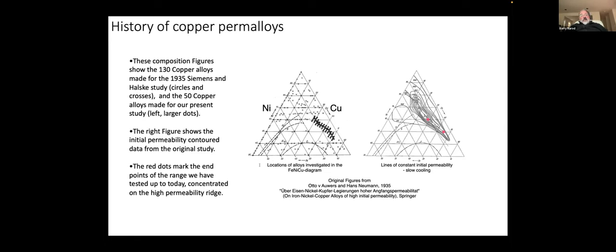Now, some of the features on this drawing show up here as various curves, which Auwers and Neumann published as estimates of a region where they were getting mechanical segregation of their elements into different crystal types, and creating permanent magnetization. So this was an area they ended up trying to avoid when looking for high permeability materials. The right triangle is their contour plot of initial permeability for a very slow cooled heat treatment. And I've marked on here in two red dots the range of alloys that we have ended up using to study this zone of copper alloys, trying to stay within this high permeability zone.